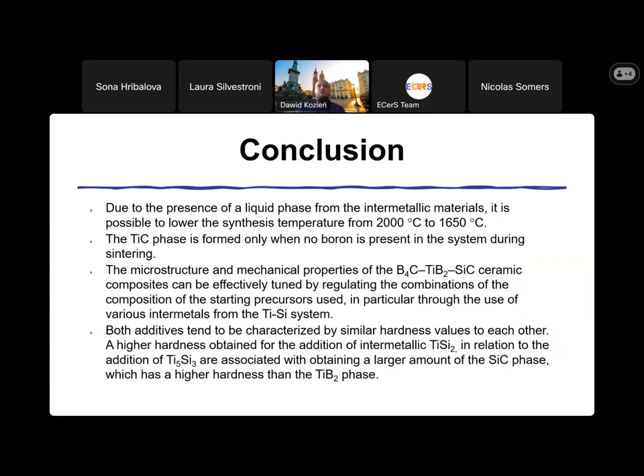So maybe to conclude, this part of my work showed that due to the presence of the liquid phase from the intermetallic material, it is possible to lower the synthesis temperature from 2000 to 1650 Celsius degrees in typical free sintering. The titanium carbide phase is formed only when no free boron is present in the system during sintering. The microstructure and mechanical properties of our obtained composite ceramic can be effectively tuned by regulating the composition of the starting precursors, in particular through the use of various intermetallics from the Ti-Si system.